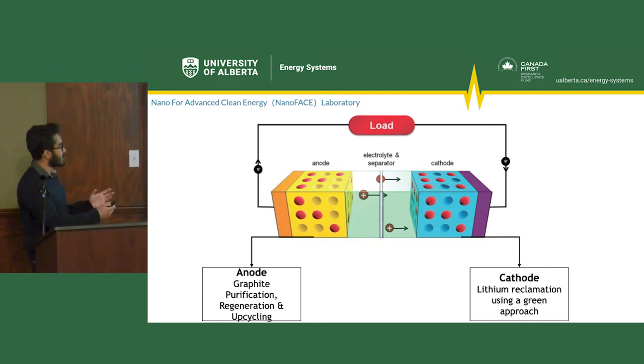So a battery has two parts, the anode and cathode, the positive and negative. And for the anode, it's usually the mineral graphite that's used. So my research focuses on taking the used or spent graphite and purifying it and regenerating it. And I'm trying to upcycle it as well. We'll get to upcycling in a bit. And in terms of the cathode, I'm trying to reclaim the spent active materials, the lithium in the active material, and use it for the next generation of batteries. And I'm using a green approach, which means the chemical composition that I'm using to reclaim the lithium is much more environmentally friendly than the traditional method used in industry.